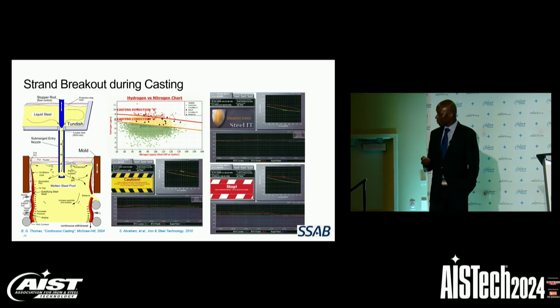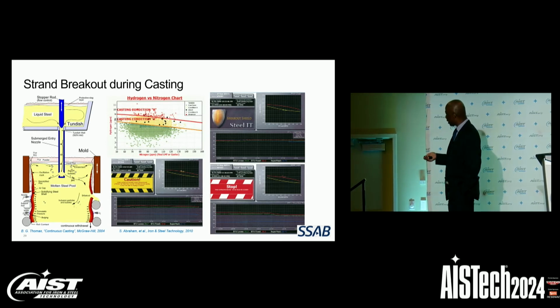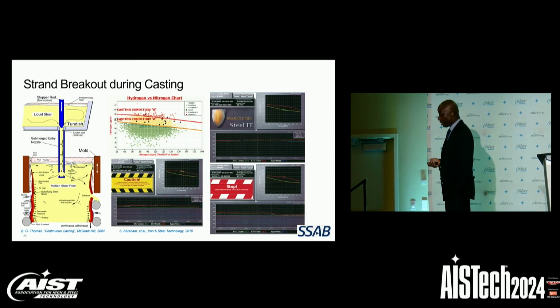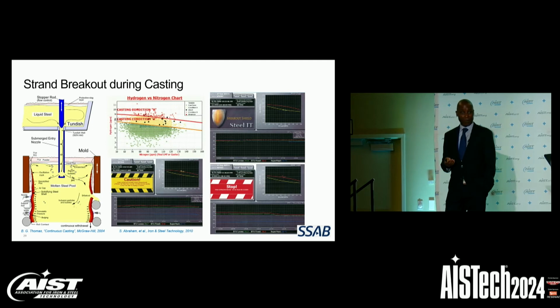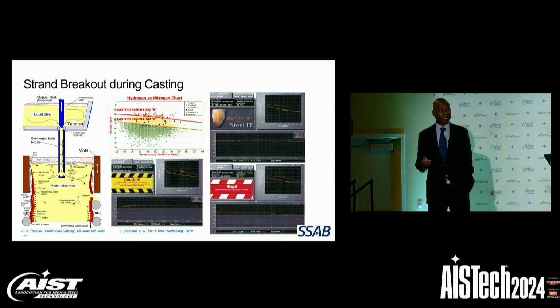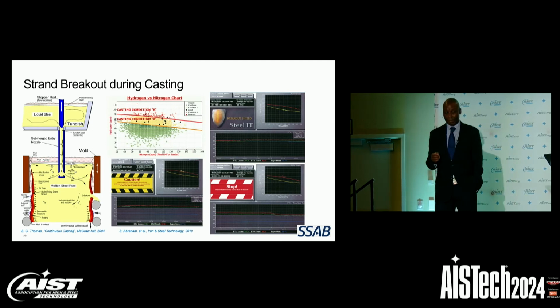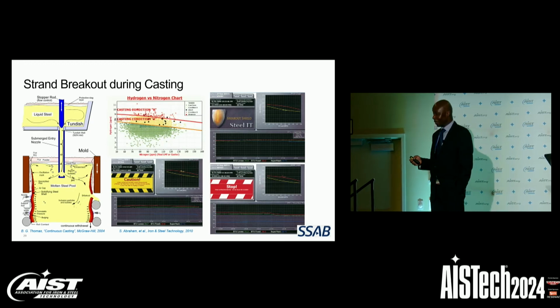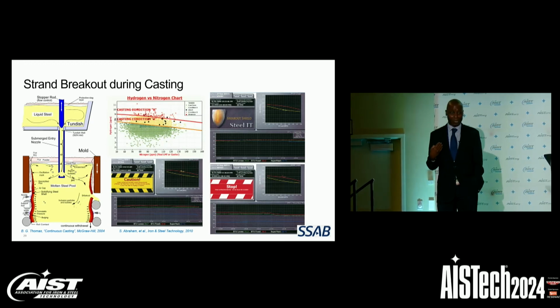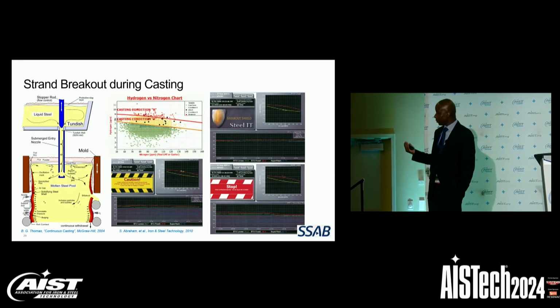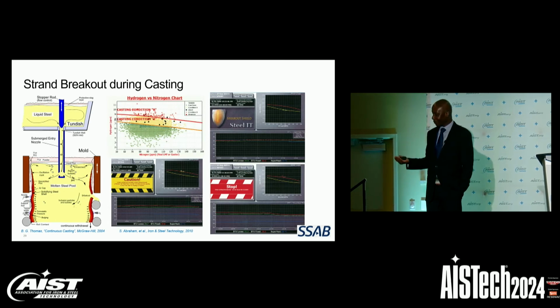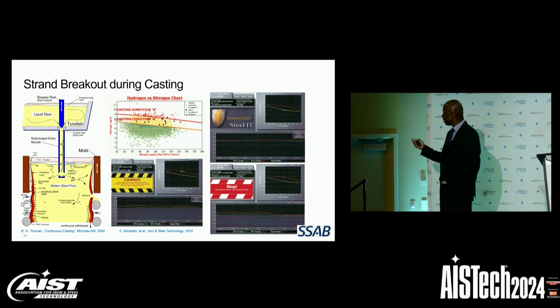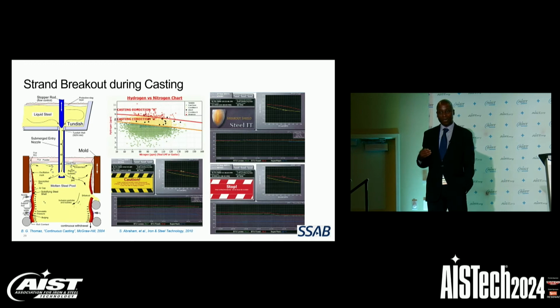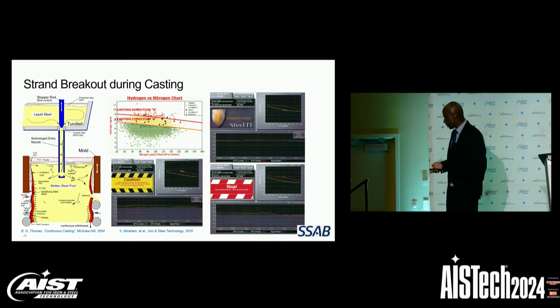Using all of this information, we developed a model to warn the caster operators of when a hydrogen-nitrogen breakout is imminent. So what you're seeing here, where the model indicated to the operator that they should stop casting, they didn't stop casting on time, and hence they did have breakout on that heat. But I should say, if you have a degasser like my company does, and you use it effectively to remove hydrogen, of course, and nitrogen, you don't have to worry about strand breakout during casting.